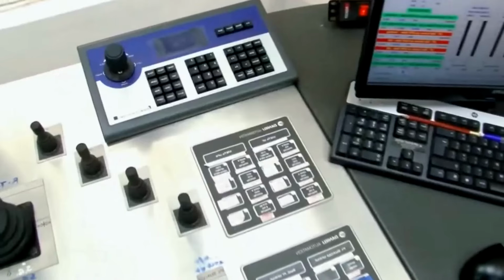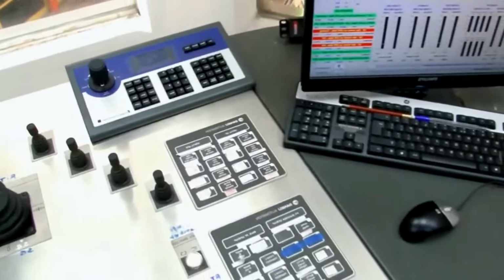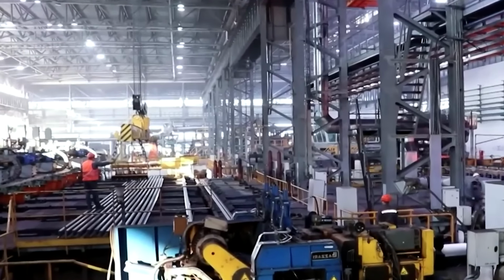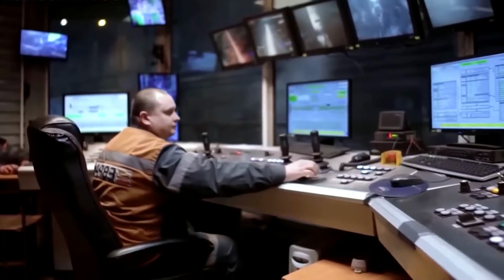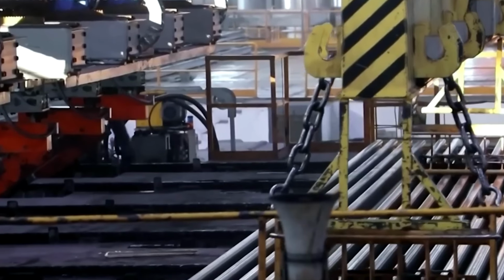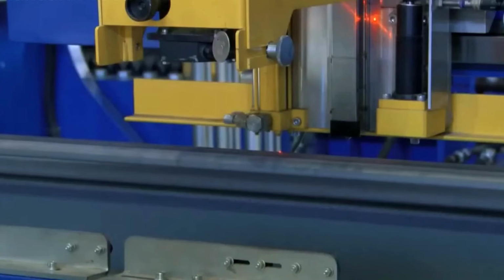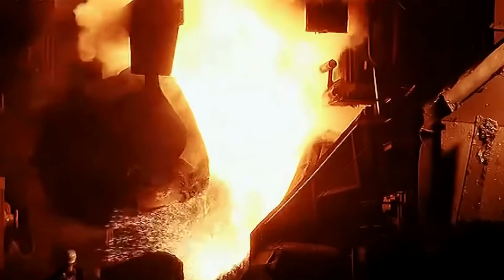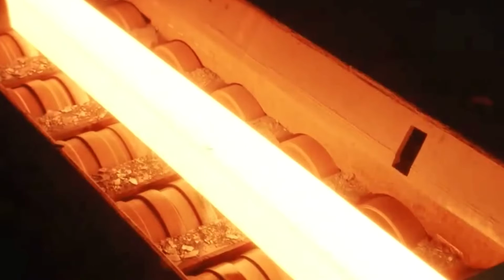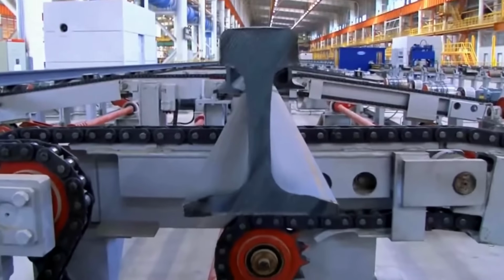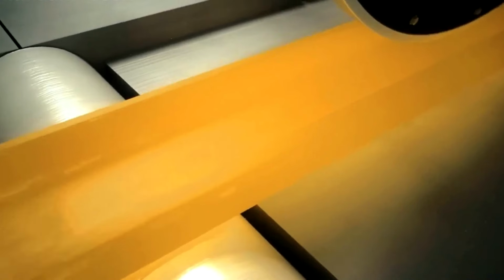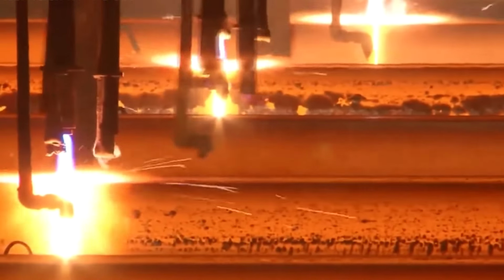of solid steel. Finished rails transfer to the automated inspection area where high-speed cameras scan the surface at microscopic resolution. Meanwhile, ultrasonic and X-ray systems examine the internal structure to detect hidden defects. Random samples undergo testing in tensile machines, compression rigs, and Rockwell hardness testers to evaluate load-bearing capacity and deformation resistance.